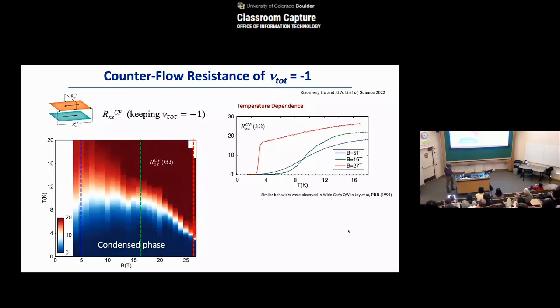But note that in high magnetic field, when we measure, this counterflow resistance stays finite but turns into a kind of zero counterflow resistance state. If I just call this not the counterflow resistance, just resistance, what does it look like? It looks like the superconducting transitions, right? Indeed, if you look at it very carefully and analyze all this behavior, which I'm going to skip through, you can show that here the transition is almost like a BCS-like transition.